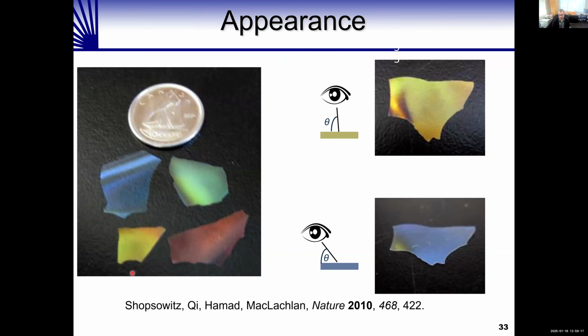Because the color originates from a diffraction property, there's a strong angle dependence on the color. If you look at the yellow film from the top and just tilt your viewing angle, it turns blue. There's actually a sine theta angle dependence on the wavelength of light reflected from these materials.